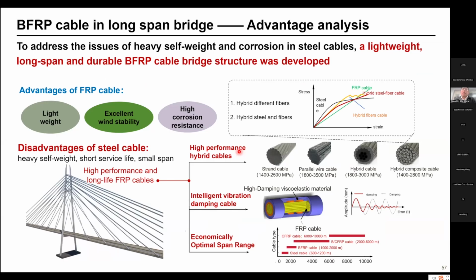Okay, next is cable. Typically we understand the FRP cable to be the CFRP cable, carbon FRP cable. Although carbon FRP cable has very good performance compared with steel cables, in some cases we can use basalt fibers to produce this cable, because it has a very high creep rupture strength. Typically, we call it 50%; for carbon fiber, 70%; glass fiber is around 30%. So it can be pretensioned for prestressing, and of course it is also suitable for cable. It can be very cost effective compared with carbon fibers.